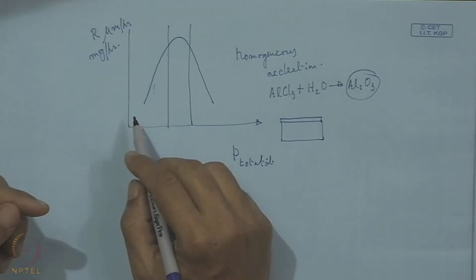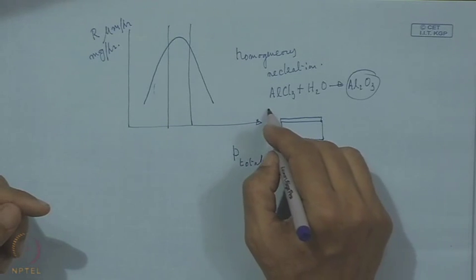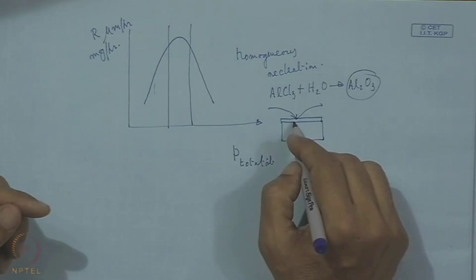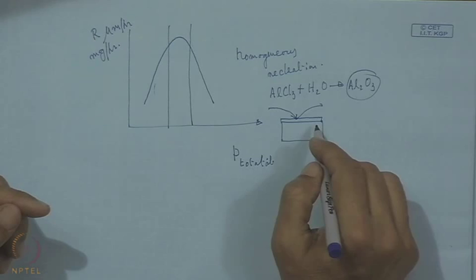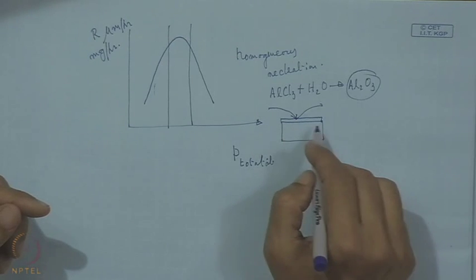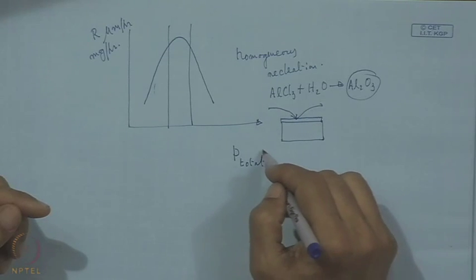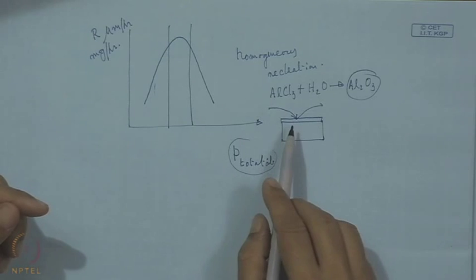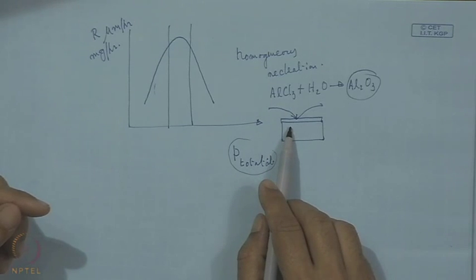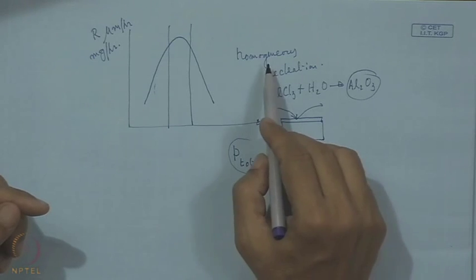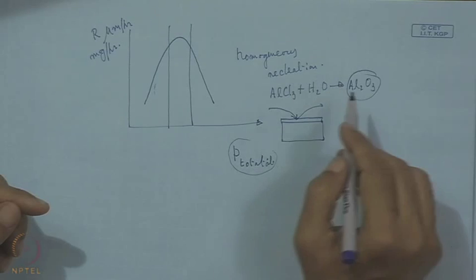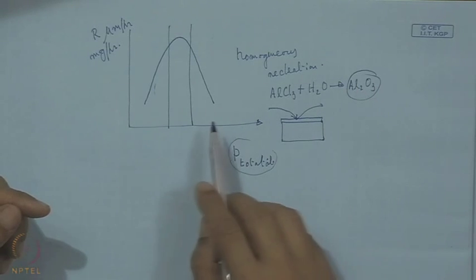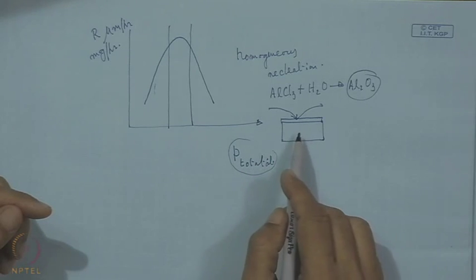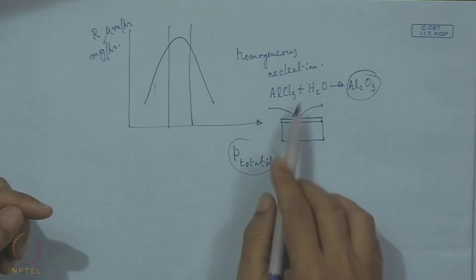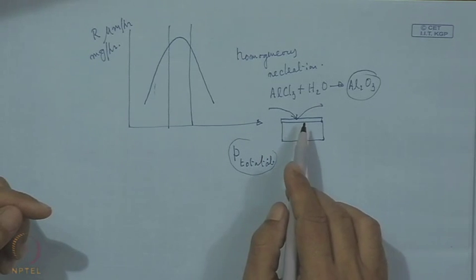And when the pressure is too low, the residence time of the incoming gas on this substrate is not enough; it is not getting enough dwell time to reside and get adsorbed on this surface. So, this is also a function of total pressure. When it is too low, the problem is with dwell time or residence time, and the problem associated with adsorption. And when it is high pressure, then it is homogeneous nucleation, that means the formation of Al2O3 is taking place in the gas phase, and this substrate does not receive much of this vapor, which could have condensed and synthesized over this surface.